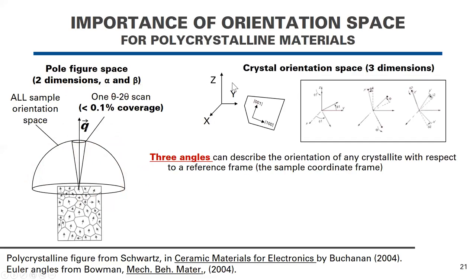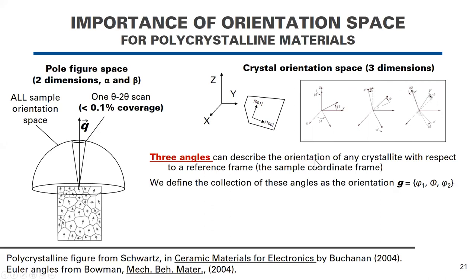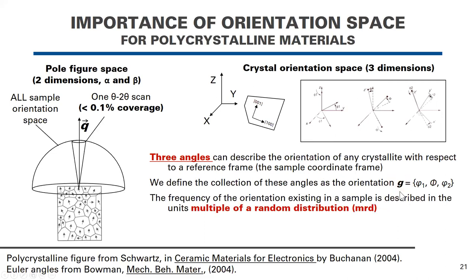If you take it one step further, you could characterize it in terms of an orientation distribution function, or ODF. And in that case, you would describe all possible crystal orientations using three dimensions, here represented as the three Euler angles. Okay? These three angles can describe the orientation of any crystallite with respect to a reference frame. One can define the collection of these angles as the orientation lowercase g.